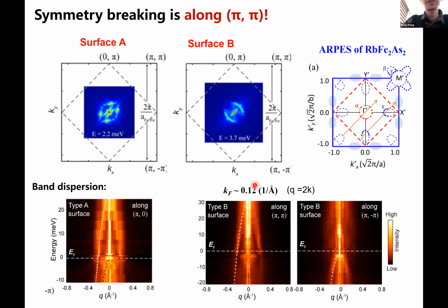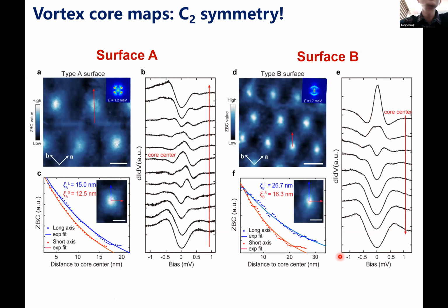And for the type B surface, you can see that if you take a line cut along different directions, along pi pi or pi minus pi, the dispersion is very different. So that's the C2 symmetry. And the C2 symmetry is also reflected in the magnetic vortex mapping. On surface A, we apply the perpendicular field, and we can observe the vortex, and it's elongated along the pi pi direction.